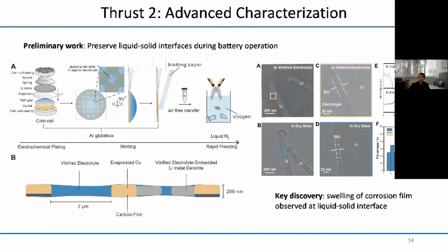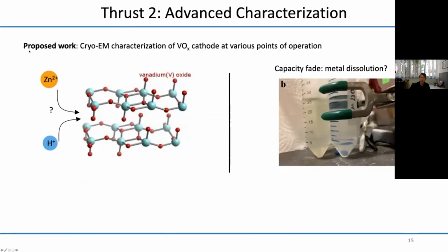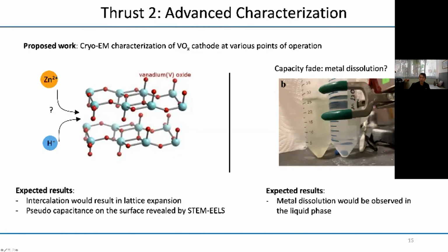And so what we can do using this technique in our proposed work is to characterize this vanadium oxide cathode at various points in the battery's operation and see, for example, if we can observe a lattice expansion in this cathode, which would be expected if intercalation were the mechanism of storage. Or, for example, if we can map out the vanadium in the liquid phase using spectroscopic measurements.